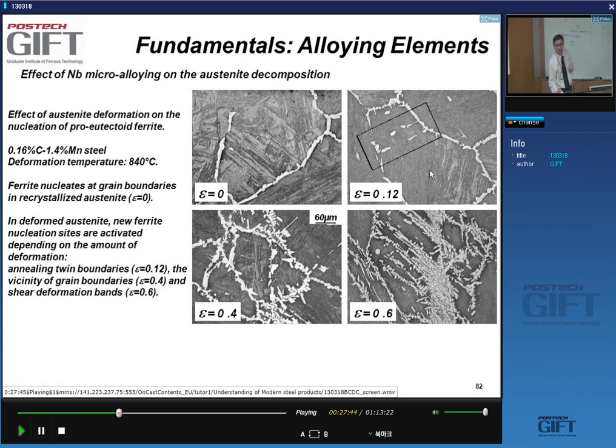my austenite grain. And as I increase the strain, I can see now that in addition to the grain boundary ferrite, I now form a lot more ferrite nuclei inside the grain. So I have found, as it were, a method to reduce the grain size of my austenite by doing the transformation not from this, but from this. Now, obviously, it can only work if you can deform the material,